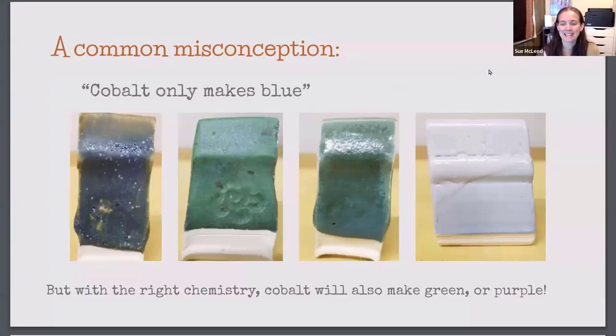A common misconception is that cobalt only makes blue. But as you can see, cobalt sometimes will make green. Sometimes you'll get blue where it breaks green, like our sapphire blue glaze is mostly blue, but where it's thin, it's green. That is often the result of titanium in the recipe. And then here's an example of where cobalt makes purple, lavender. So with the right chemistry, cobalt will also make green or purple.